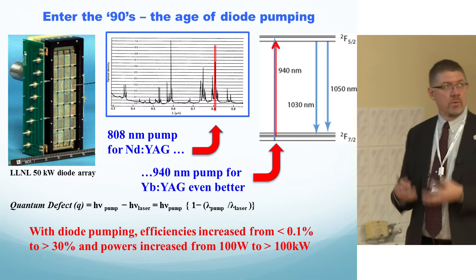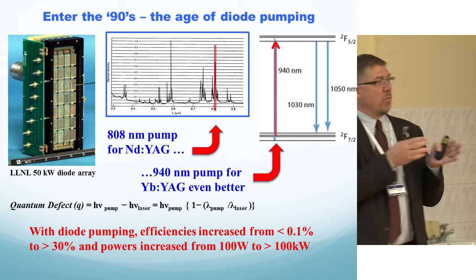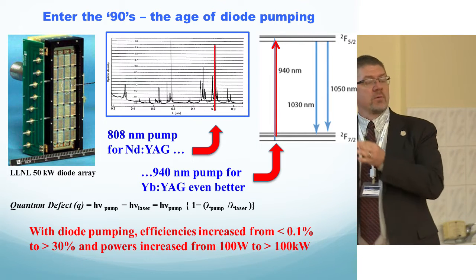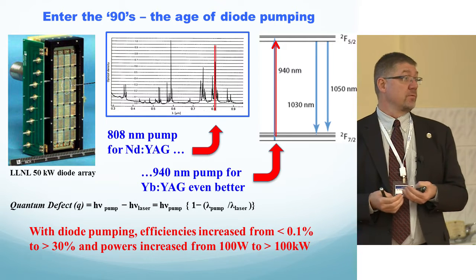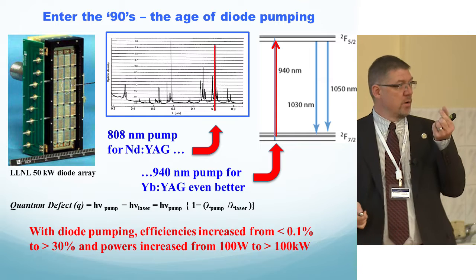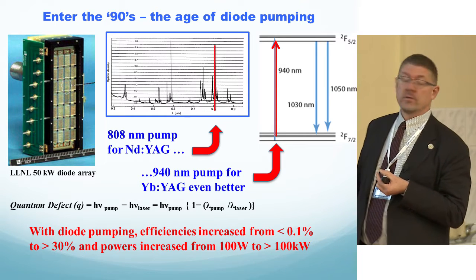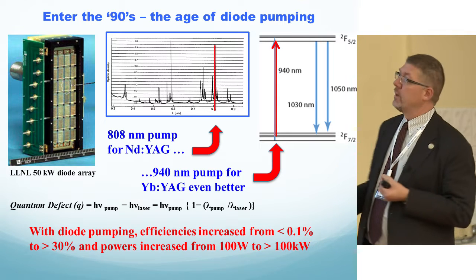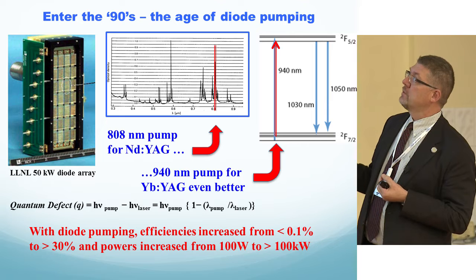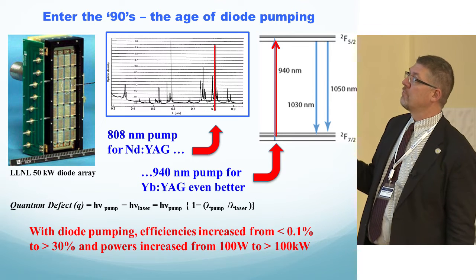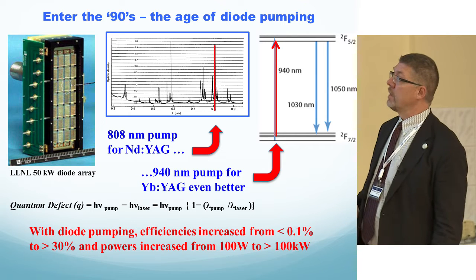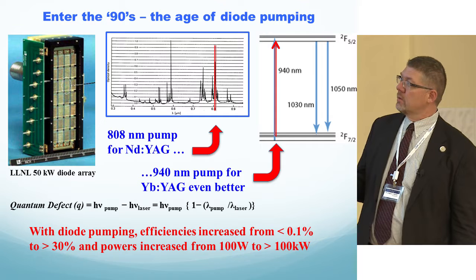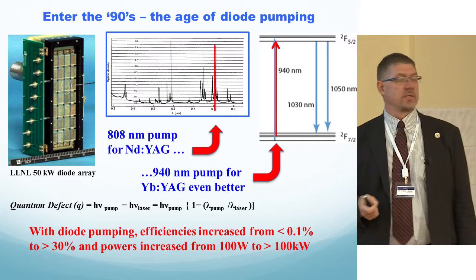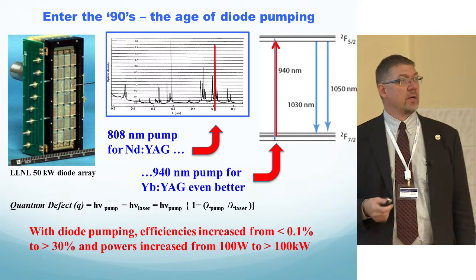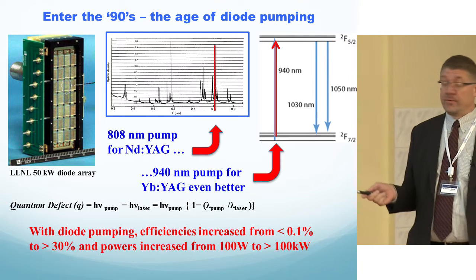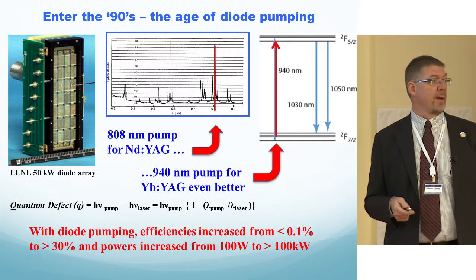So when I was working with the Navy, late 1980s, early 1990s, we started moving away from flash lamps because Sony and Spectra Diode Labs and many other companies were starting to develop high power diodes. The beauty of the high power diode is it had a fairly narrow spectral output, which could couple very well to the absorption lines in the rare earth or the transition metal ions. For neodymium, you could pump at 808. For the ytterbium that we heard about earlier today, you can pump at 940 and lase between 1030 and 1050 nanometers. The good thing is it took laser efficiencies up from about 0.1% wall plug to greater than 30% today. Which is reasonable. It also took laser output powers up. In 1987, the highest output power recorded was about 100 watts.